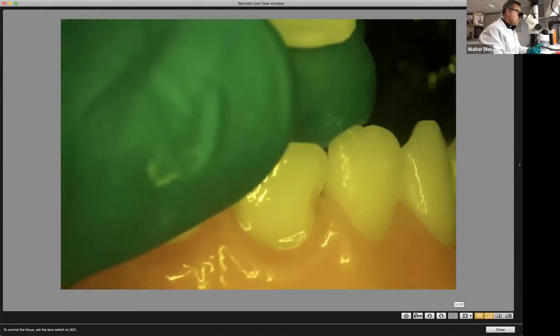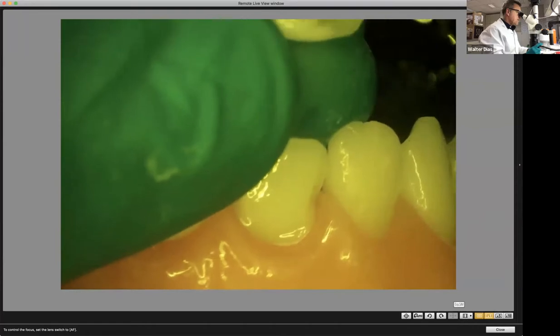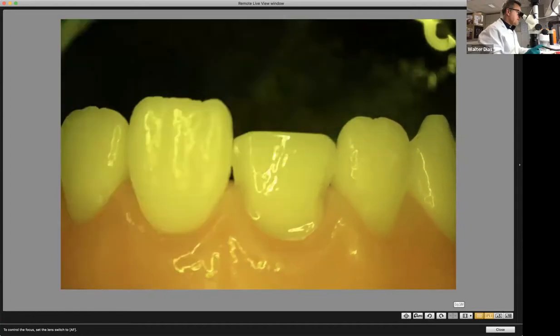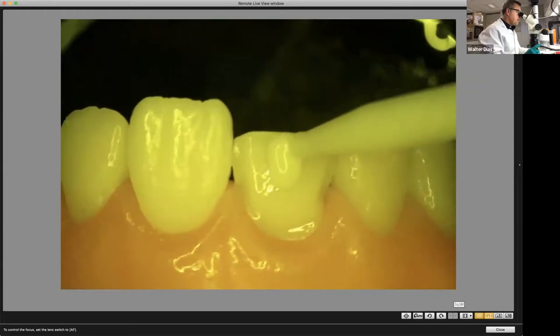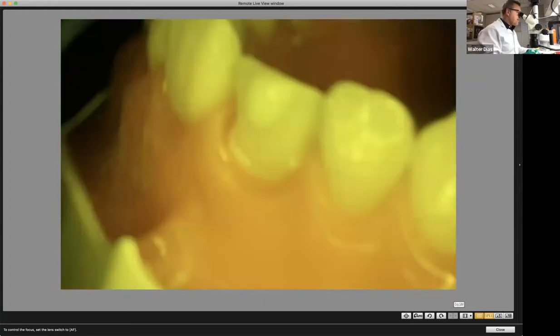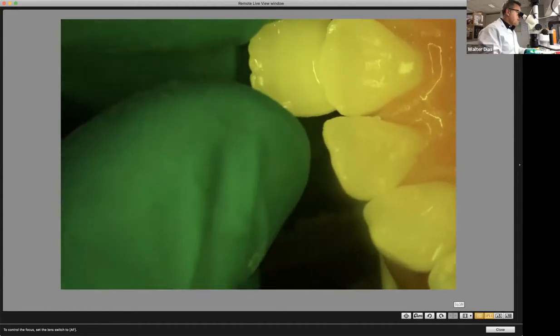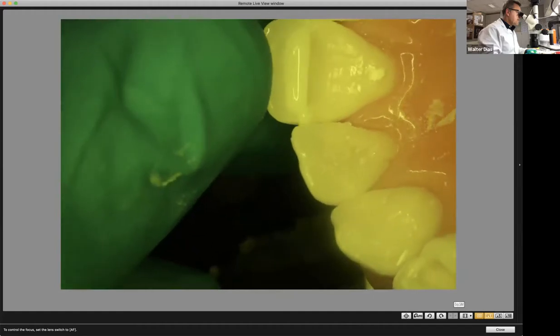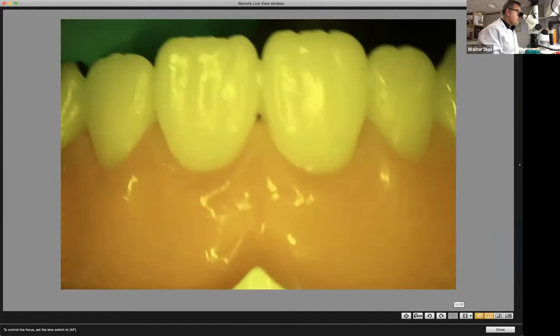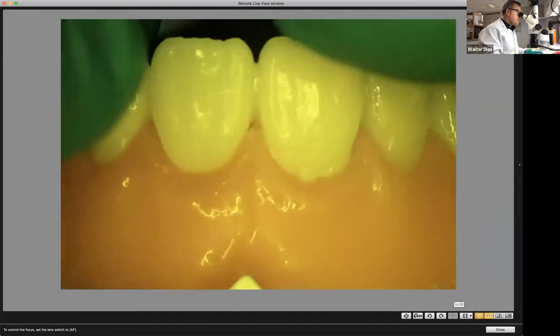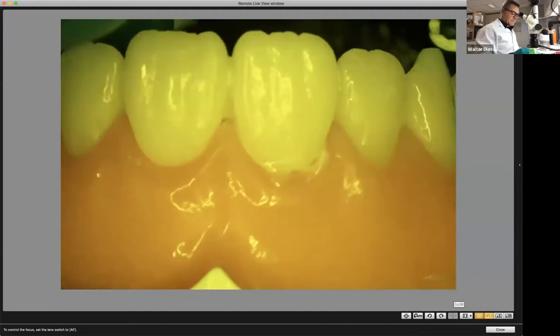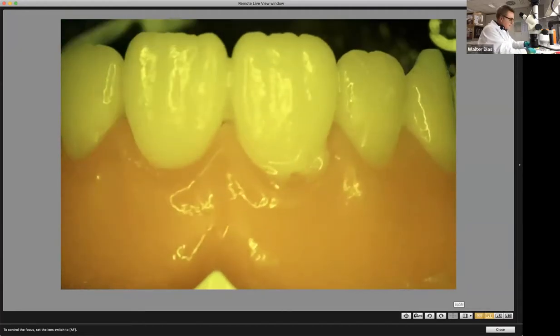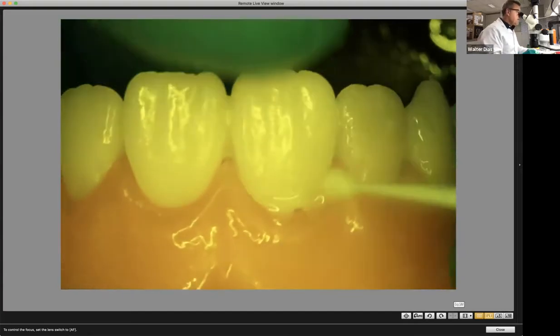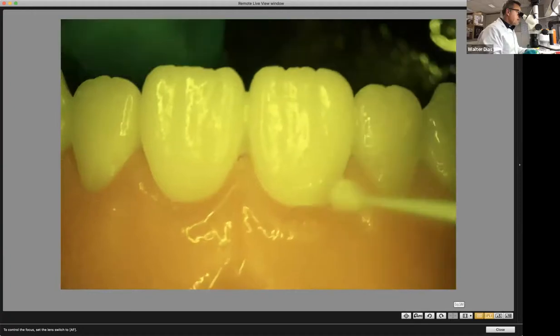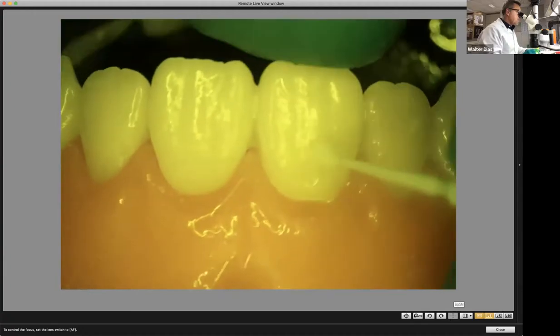What you do is you put it here. Make sure you don't trap any air bubbles. And then I like to put a little dab on the tooth here, because when I add the veneer to the tooth, it's the cement touching the cement. Look at this. The cement touching the cement. Very well. And now we start removing the excess, and you can wait for the final gel phase, or you can tack cure this to your preference.